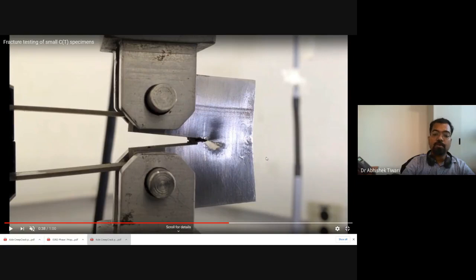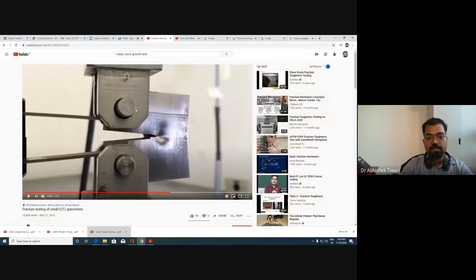So if you are loading monotonically inside the furnace at high temperature, then that test will be a creep test, a creep crack growth test. And if you are loading cyclically at high temperature, then that will be called a creep fatigue crack growth test. That's a combination of creep deformation plus fatigue deformation, and you have a crack also in the system. So this is for your visualization of what happens; we have discussed the mechanism, and there is another video which will explain a few things about how material deforms.